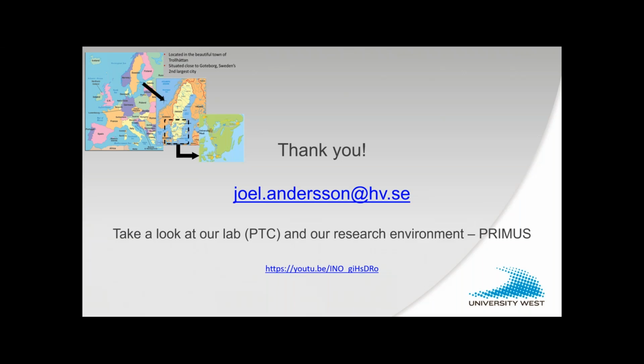Okay, very good. For SAC testing, is there an applied stress prior to the heat treatment to account for residual stress simulation and stress relaxation during heating, or do you just pull to failure after aging at temperature? What we did was just to pull to failure after heat treatment. We did not have any pre-stress. Okay, just my own personal thought: would you expect there to be any kind of effect of a pre-stress, say a residual stress existing in a component?